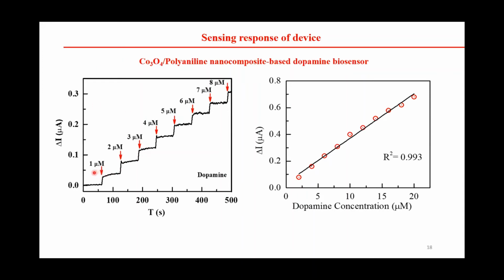From the low concentration, we do chronoamperometry, and the same kind of change in current can be observed. This is a measurement from the potentiostat, in which we apply the potential and measure the current at different times. Suppose at 50 seconds or 75 seconds, we can see the current is increasing. When we increase the dopamine concentration in the liquid in which our electrode is dipped, we see the concentration is increased, and the change in current is also increasing.